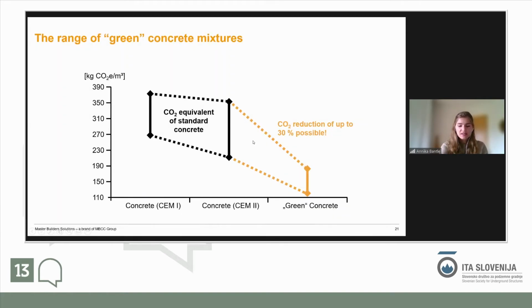But these composite concretes are also very interesting for greener concretes. And we want to look here at this very basic diagram where you see the CO2 in kg per cubic meter. And you have here the different types of cements or concretes that are made with different types of cements. And you see that standard concrete with a CEM I reaches from around 270 kg of CO2 up to almost 390, whilst a composite cement with CEM II/A, for example, or CEM II/B even, will be already a bit lower, and you have a broader range of pushing this CO2 content for a cubic meter of concrete.